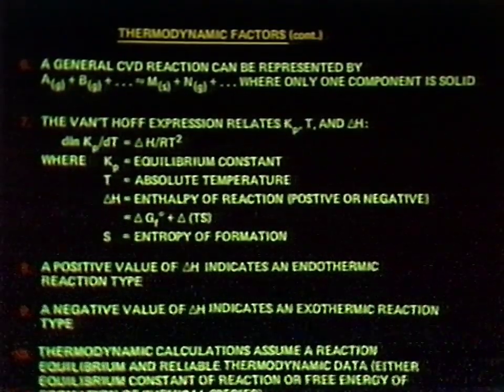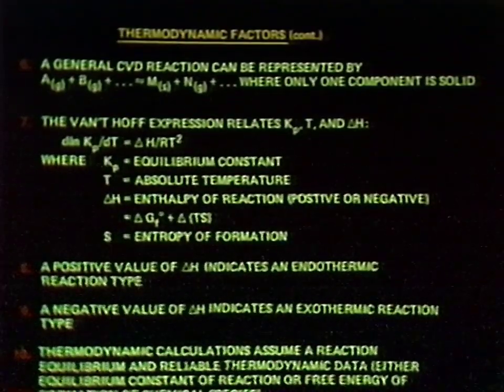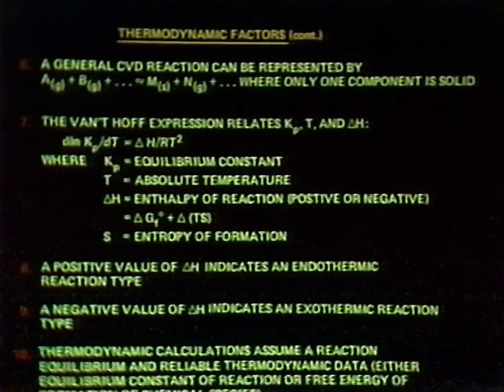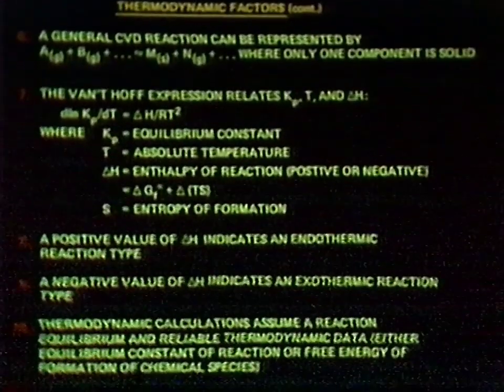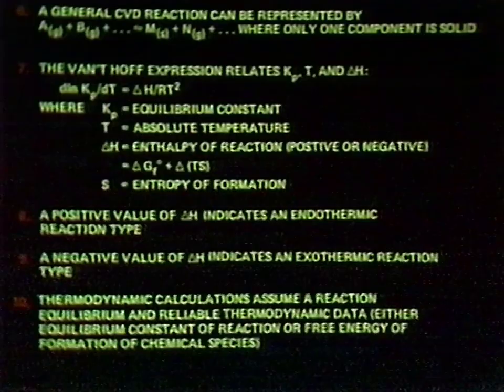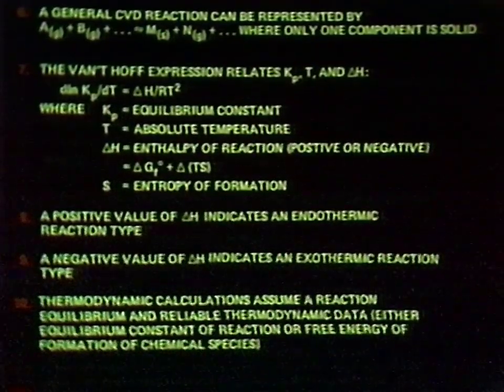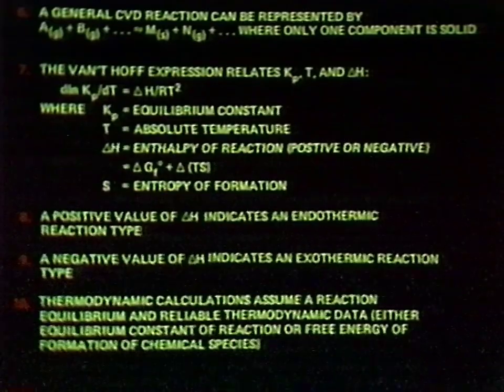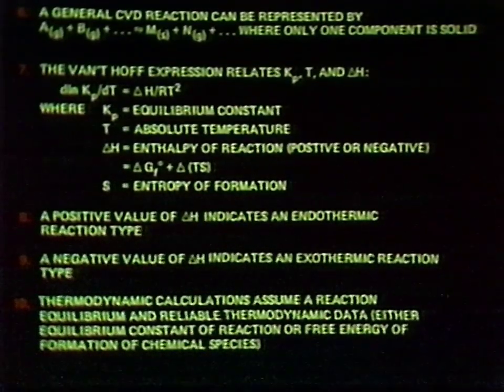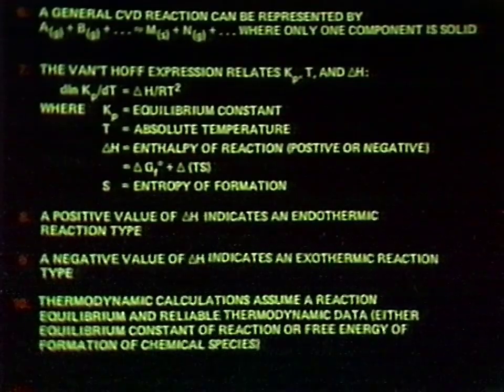The thermodynamic calculations assume a reaction equilibrium, and they also assume the availability of thermodynamic data, which is not always the case. The equilibrium, of course, is another thing. CVD reactions are rarely or hardly ever in full equilibrium, so it is quite an assumption one has to make. However, it does give us an initial starting point to see whether a reaction is feasible or to what extent one can expect it to run. Okay, so far for the thermodynamics in general.